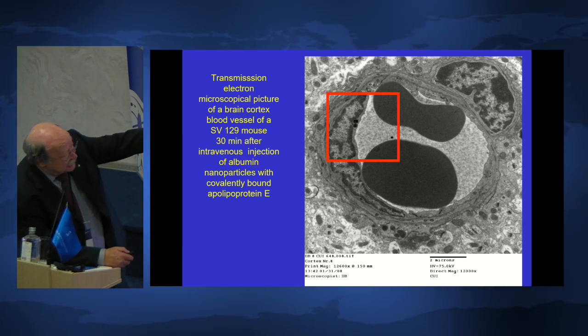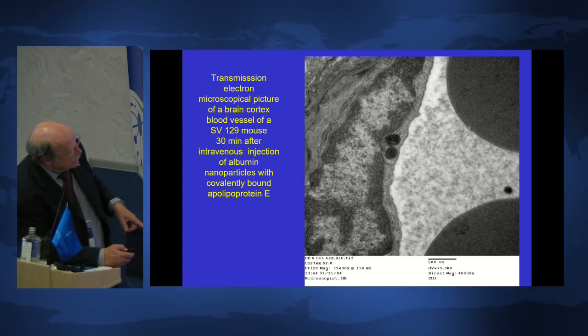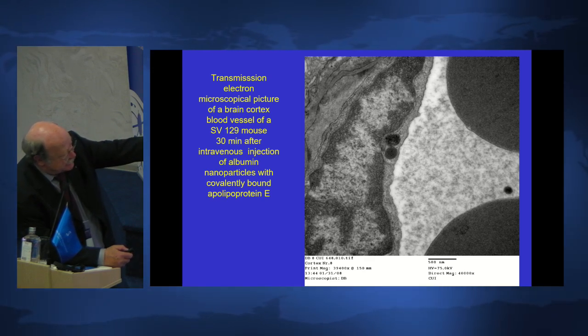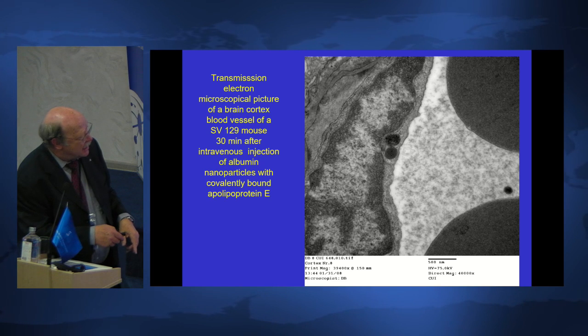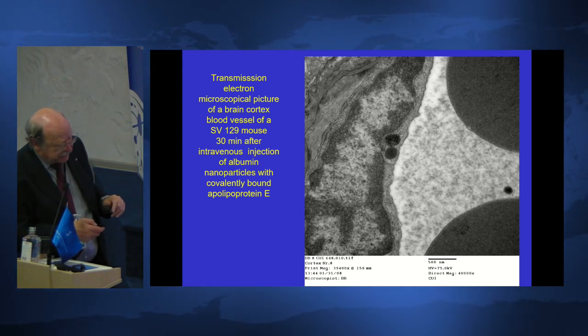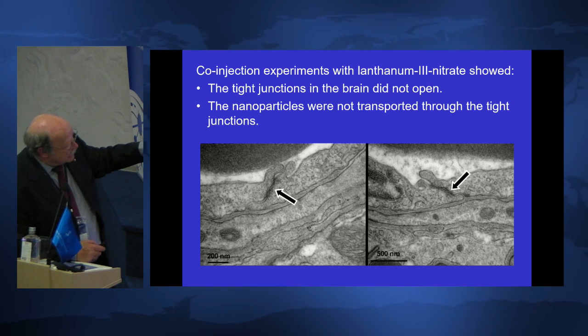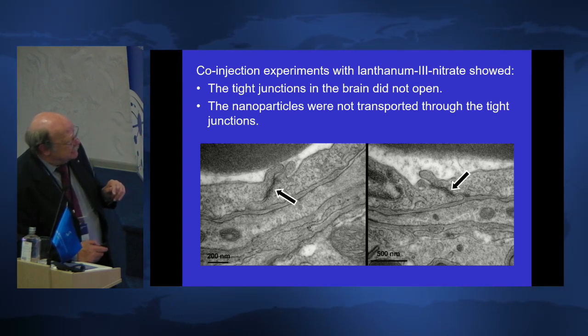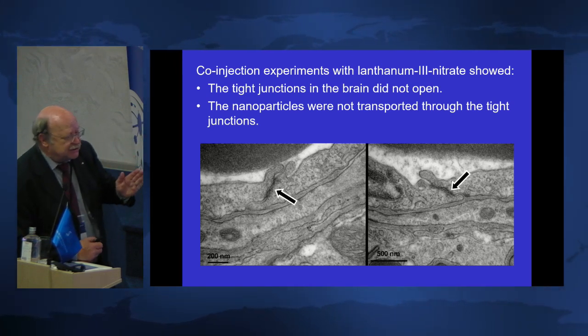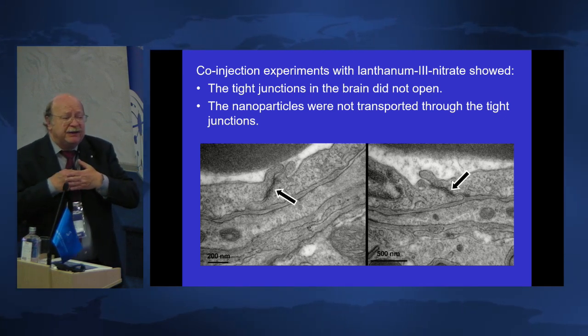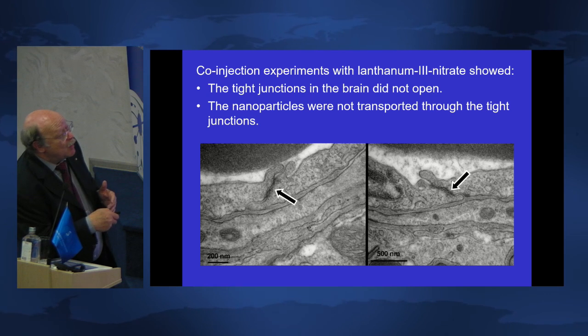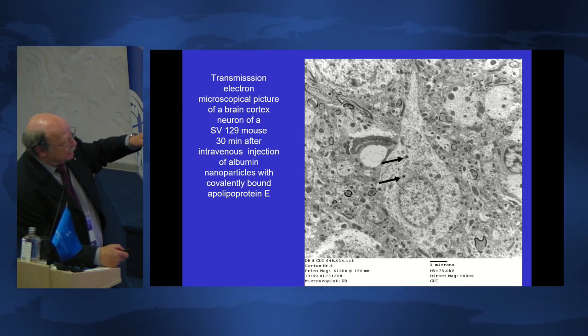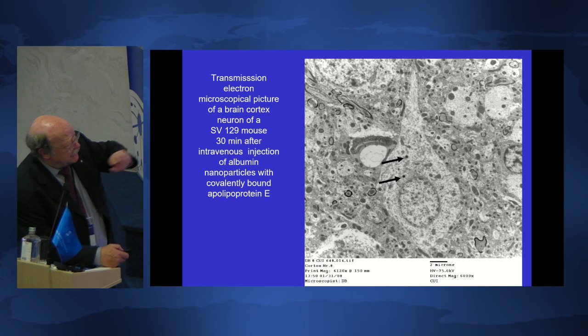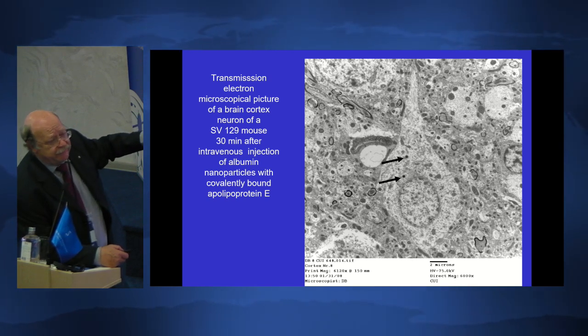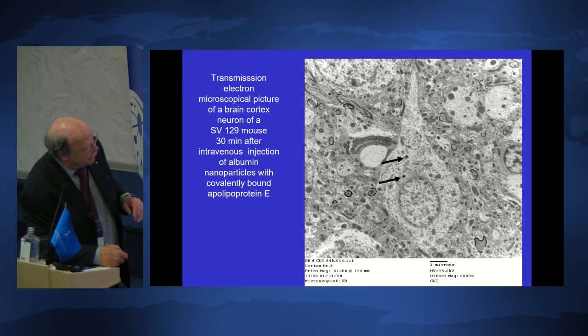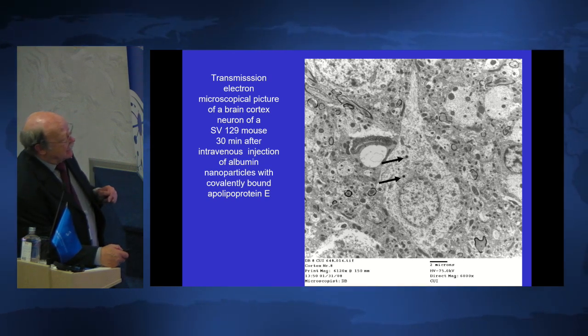And when you magnify this picture in the next slide, you can see this one nanoparticle still in the lumen and two other nanoparticles in the endothelial cells. And what we also found with lanthanum nitrate is that the tight junctions remain closed. So the nanoparticles access the brain by transcytosis. And after about 15 minutes, you can detect nanoparticles all over the brain. Here we see two nanoparticles in a neuron.